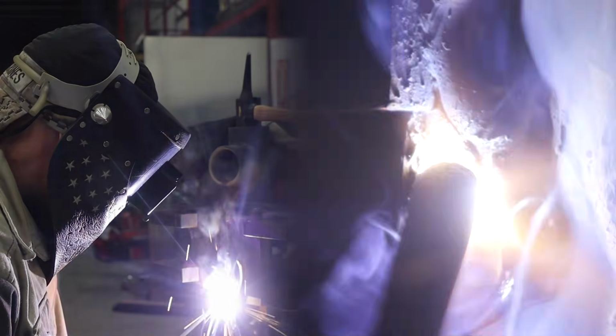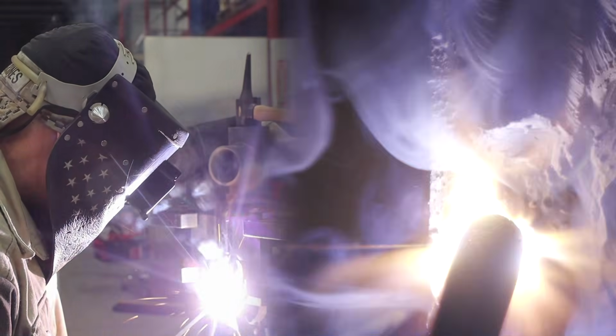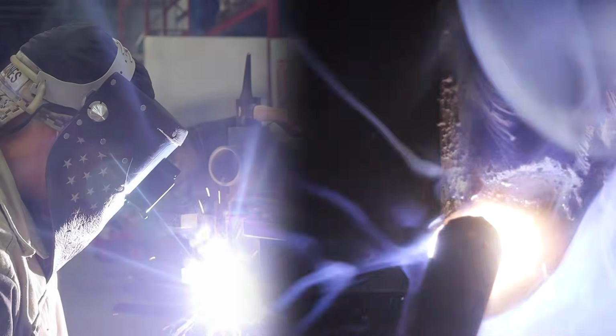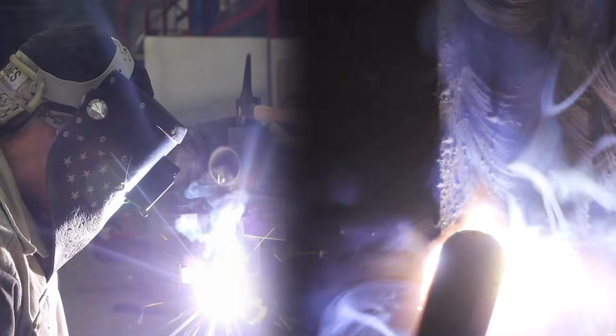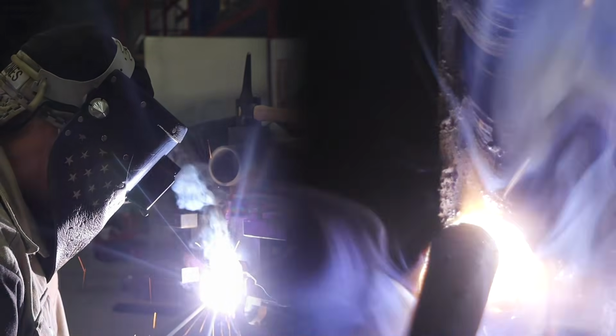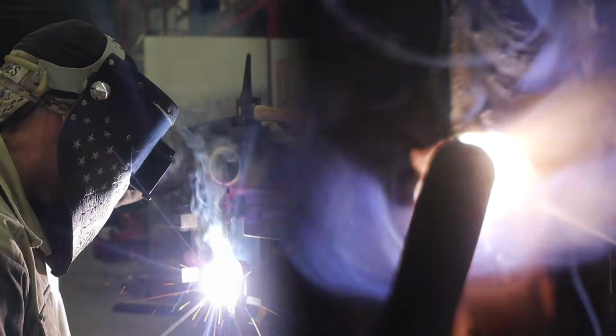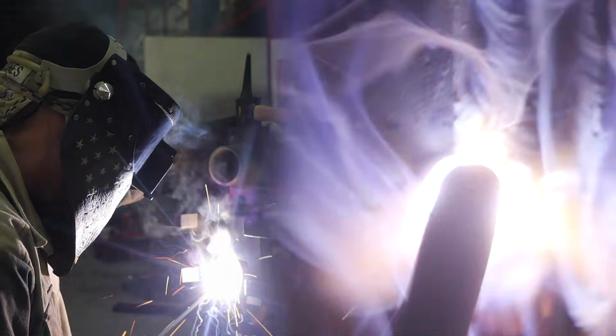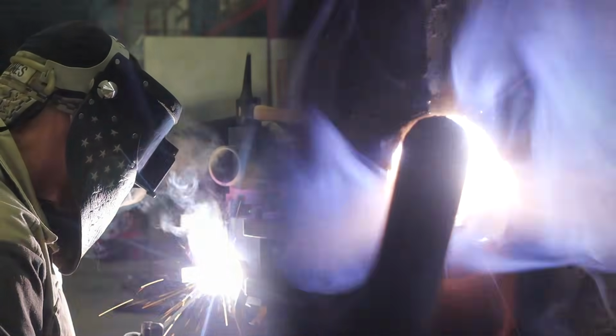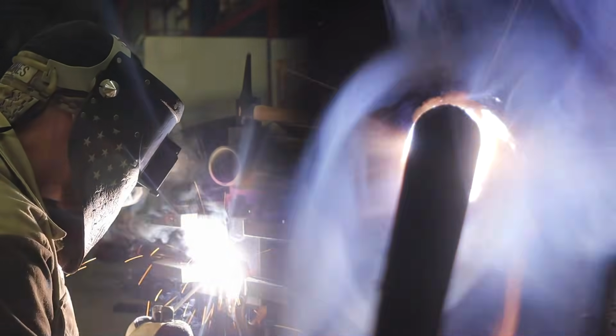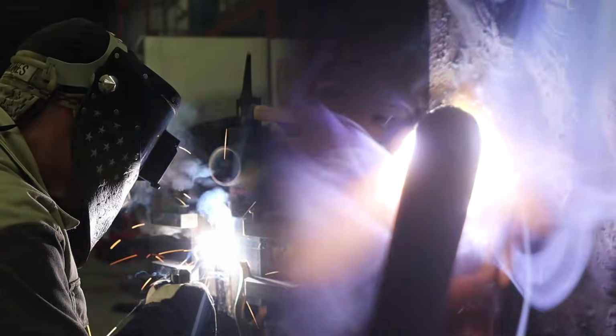What I like to do is use what's remaining of the top edge of that bevel as the center line of my pass, and come over just past that corner, that edge, about 1/8 of an inch, and just completely decimate it, right? That's the center line of my weld, the edge of that plate. That way I'm guaranteed to get a good tie-in to the top side of this plate.